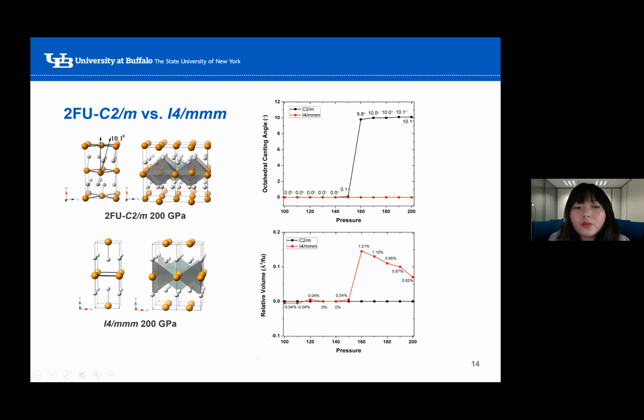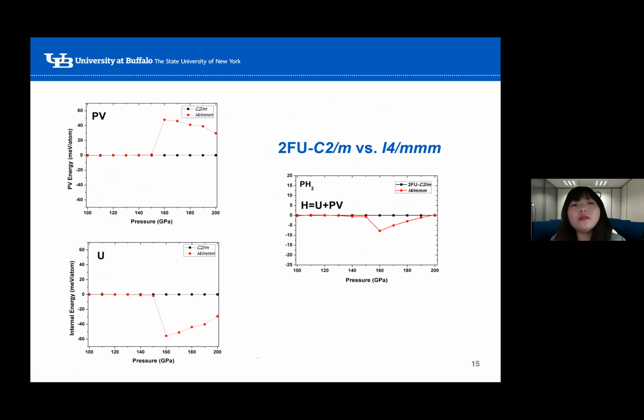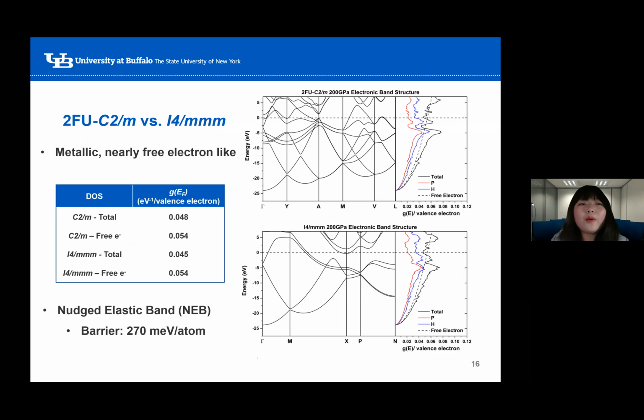Although the PH bond distance within I4/mmm is shorter, the canting of hydrogen in the C2/m phase results in a more efficient packing and therefore a smaller volume for the C2/m at higher pressures. So the smaller volume of C2/m also results in a smaller PV contribution to the enthalpy. However, because the electronic contribution favors the I4/mmm structure, the I4/mmm structure is preferred by a few meV per atom. But at 200 GPa, these two structures become almost isoenthalpic. Both of the structures are metallic, similar to the 100 GPa 5 formula unit C2/m. They are all nearly free electron-like.